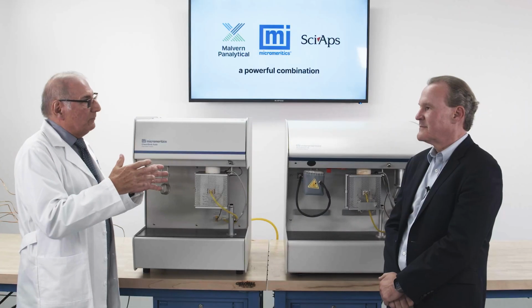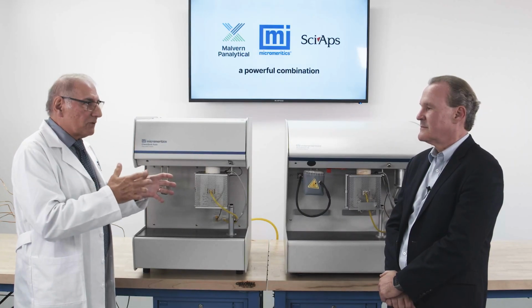So in this case, we saturate the sample with ammonia and we do desorption with a temperature program. We program the temperature to go up from room temperature after saturation, and we can see how the ammonia desorbs from the sample as a function of temperature. Therefore, we can quantify the amount of acid sites available for the reaction at the reaction condition.